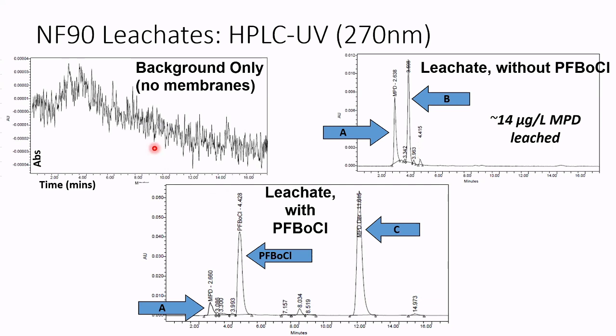So what we saw was kind of interesting. Here's a control sample that had no membranes, just the laboratory grade water on the shaker. Here we saw that there were several peaks of leachate when we added the membrane in, extracted the membrane, and concentrated the sample. And we see that we do have 2 peaks not present in the background sample, which means, based on UV data, that something's coming off of these membranes and we don't quite know what that is.